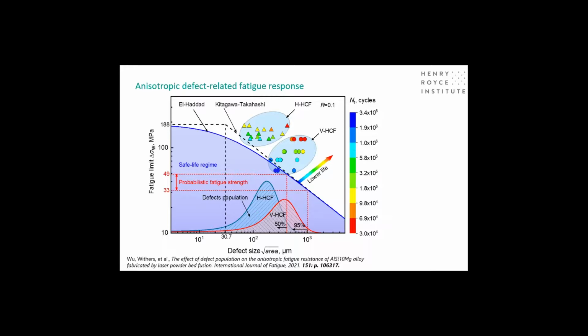So I think the take-home message here is that by scanning with X-ray CT, you can plot the distribution of the defects, as you can see on the bottom. We can see that the defects present different areas in the horizontal and the vertical test directions, and those give rise to lifetime predictions that enable us to make estimates of the safe life of additively manufactured parts.